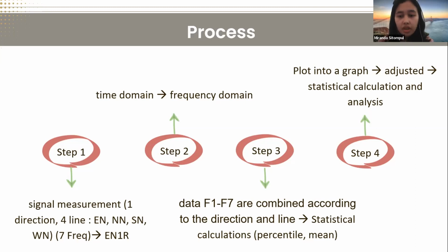After measuring, the data obtained is data in time domain, and we convert it to frequency domain with Fourier transform in MATLAB. And the data of the frequency and spectral amplitude values are separated for each measurement direction. Then the data from F1 until F7 are combined according to direction of measurement. And then we process the data with statistical calculation, for example percentile and mean, because repeated measurements are carried out at several points. So we get 4 tables for each radius. And then we plot the data into a graph, and if the data have outlier data, we repair or adjust the data. After the data has been adjusted and the resulting graph is as expected, then we perform statistical analysis.